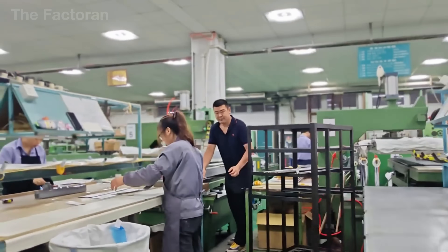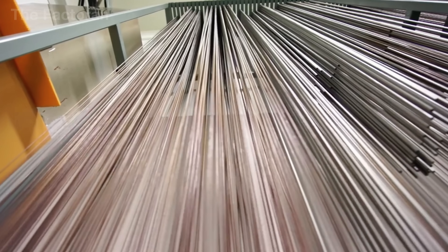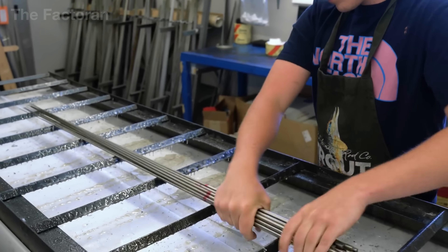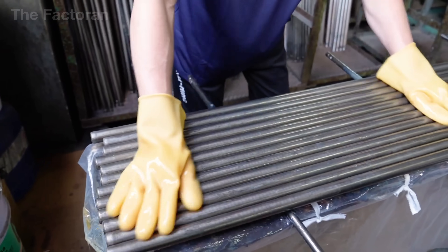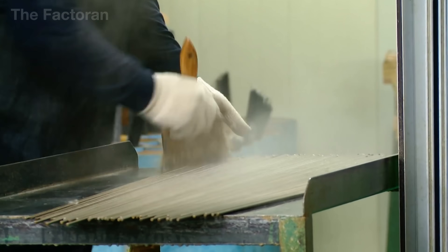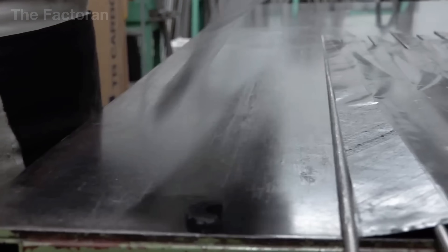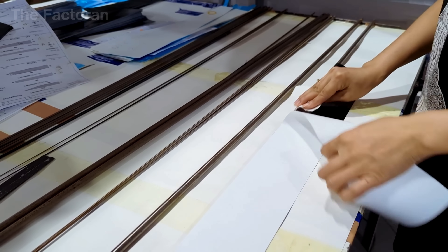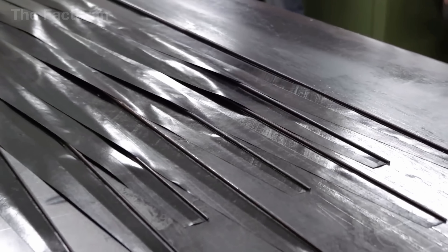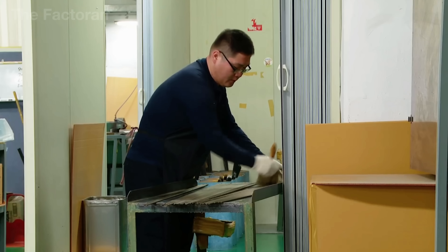The material must be positioned precisely onto the mandrel, a stainless steel shaft that serves as the internal forming mold for the rod blank. The mandrel is typically treated with a non-stick release agent so that, after heating, the finished blank can be separated cleanly and without damage. Once adhesive is evenly applied along the steel shaft, the technician uses a small heated iron to hot-tack the first layer of material into place. Each carbon piece is aligned carefully along the mandrel's centerline, squared at both the tip and butt ends, and only then secured. There are no robots or laser guides involved at this stage — everything depends on the technician's trained eye and experience.